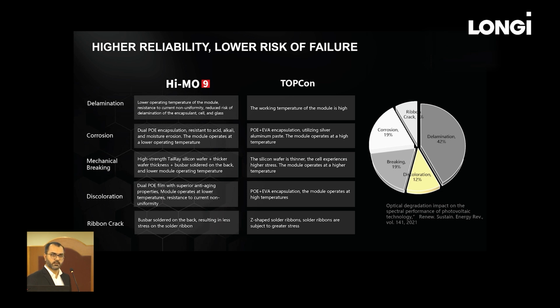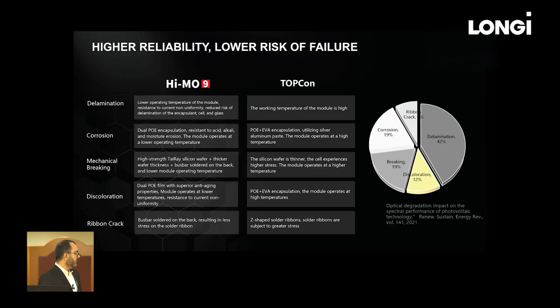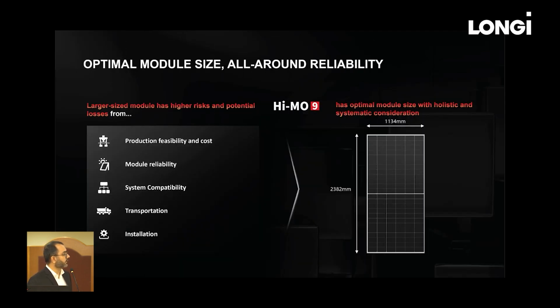Corrosion. So again, in this part, the encapsulation plays an important role. Mechanical breaking. So high strength wafer can reduce this issue. Discoloration. So again, it comes to the encapsulation part. When the humidity or moisture can enter into the encapsulation, then the discoloration will happen. We have seen the yellow modules usually. And ribbon cracks. So ribbon cracks happen because of the stress on the edges of the module.